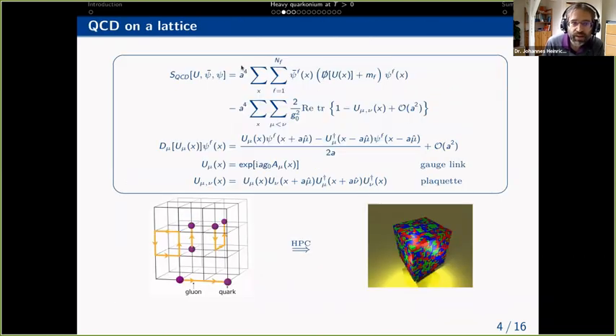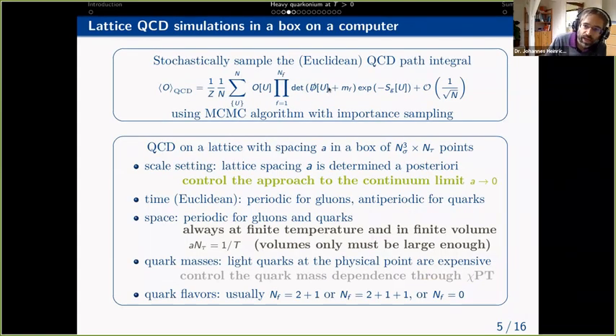So the idea for lattice is we take the QCD action, we discretize it on a grid, having quarks and anti-quarks living on the sites of the grid and the gluons on the links in between. Then we sample this stochastically with high performance computing and then just sort of integrate this numerically. That's the main idea. In order to be able to do this numeric integration, we need to use importance sampling, which forces us to switch from the real-time formalism to an imaginary time formalism in order to have this exponential of the action with a real prefactor, minus the action, instead of plus i times the action, which would be violently oscillating. And put this into a box to have an IR cutoff for a finite volume.